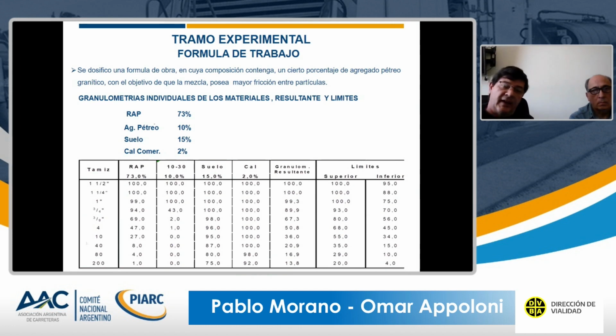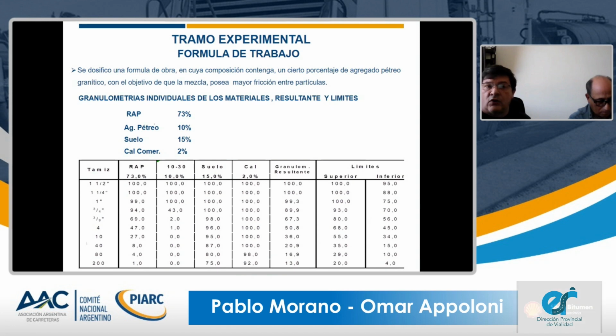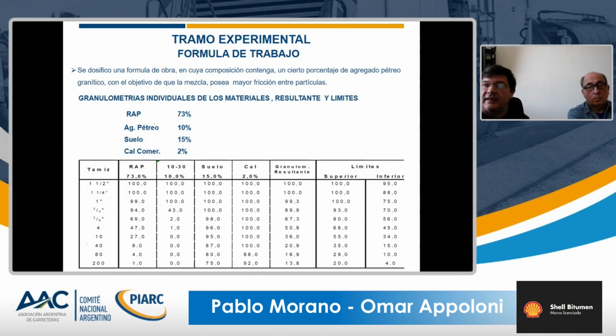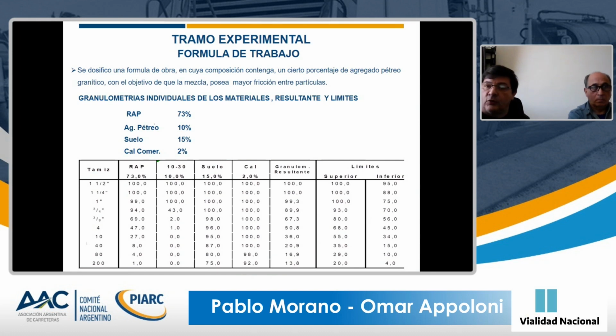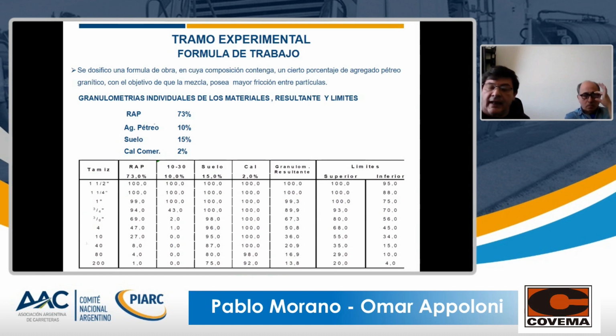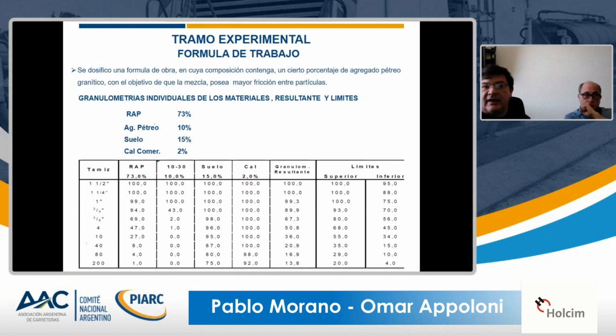Based on that, then after a few years, we tried to do a test run on a road where there were works. We got to a stretch that we could use as experimental with 3 characteristics. One was the original design of the road, and the second one with granular stabilization and foamed asphalt with a base that was covered with 2 layers of asphalt mix. One was 5 centimeters and the second one was 10 centimeters in thickness.